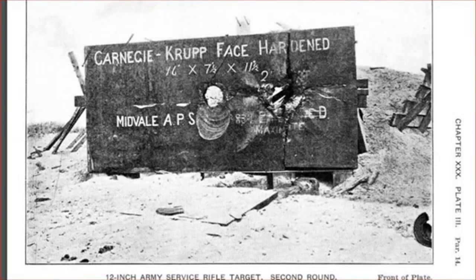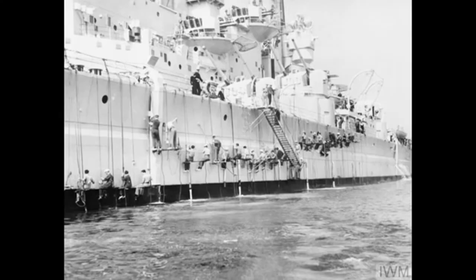into World War II. As by now it was just as much the technique used to make the plate that made a difference as much as the material properties of the basic steel itself. Now, as an interesting side note, British armour, which we covered earlier, had the opposite issue. It had a thinner than average face, backed by absurdly high tensile strength ductile steel, which made the armour massively resistive against the largest battleship projectiles, but at the same time left British cruisers slightly more vulnerable than most.